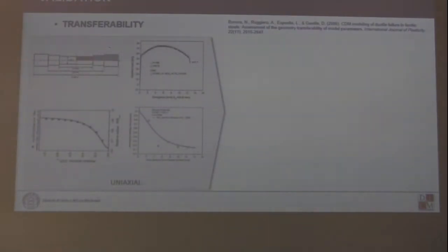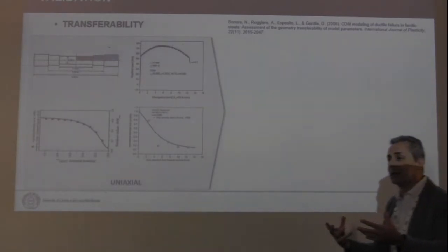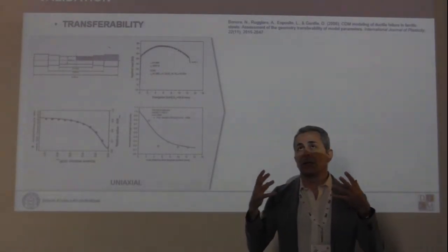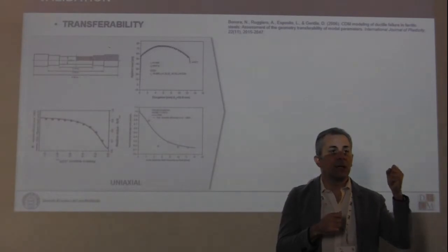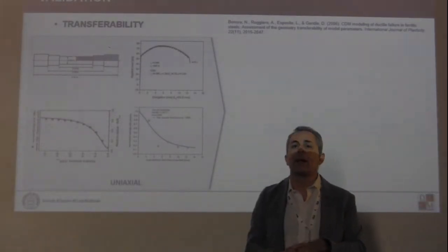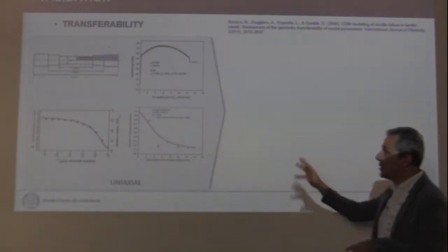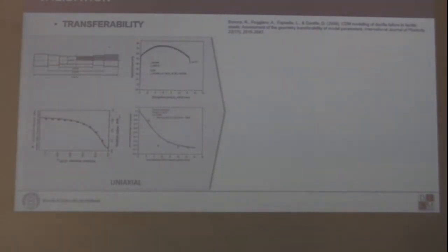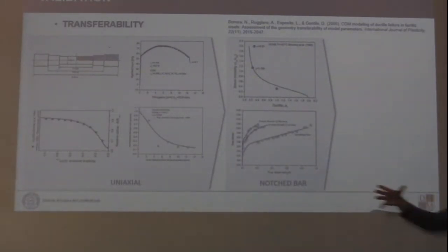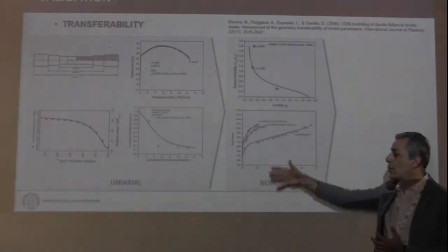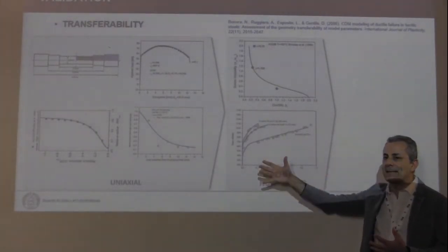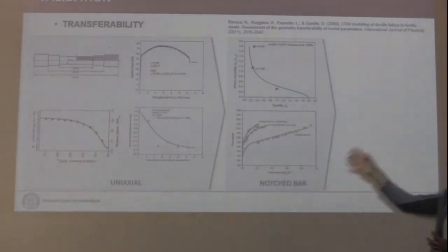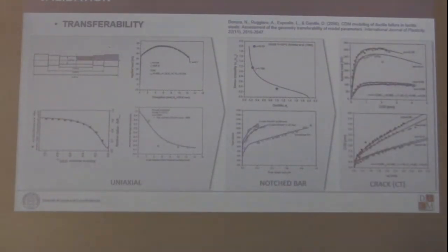Transferability has to be proved with respect to the complex stress state. So you go from the uniaxial stress state to the multi-axial stress state, but also to different loading conditions. Just to go very quickly on this, in the past we spent a lot of time in order to demonstrate the transferability. We identify tests under uniaxial stress condition, then we transfer that on a multi-axial set of stress for notches, and this provides the basis for the identification of the damage model parameters, and finally we predict without no need